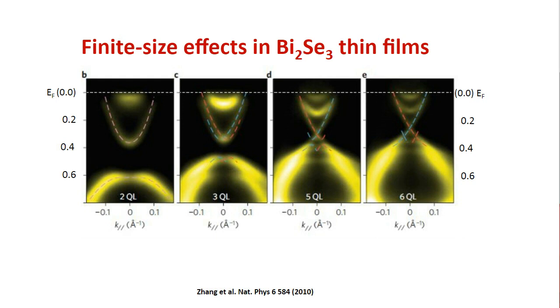Now, bismuth selenide, technically when I say 2 layers, this is a very complicated material. You have 2 bismuth atoms and 3 selenium atoms. Each layer is called a quintuple layer, which has 2 layers of bismuth and 3 layers of selenium. That makes 1 quintuple layer. So 2 quintuple layers is 10 layers of atoms, but it's 2 complete chemical cells of bismuth selenide. Okay, so you have 2, 3, 4, 2, 3, 5, and 6.